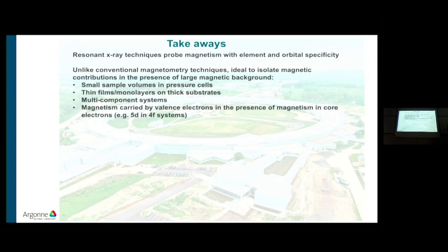Resonant techniques can probe magnetism with element and orbital specificity. These are ideal to isolate magnetic contributions in the presence of very large magnetic backgrounds: small sample volumes in pressure cells, thin films, monolayers, and thick substrates, multi-component systems, and also magnetism carried by valence electrons that are not the primary electrons. For example, in rare earths, most of the magnetism is in 4f electrons. But the 5D electrons are super important because they mediate the indirect exchange, usually referred to as RKKY interactions. So you can probe the polarization of the 5D states as they bridge these magnetic interactions.